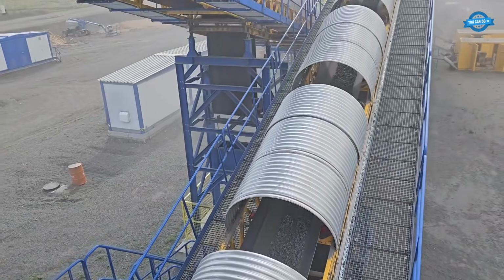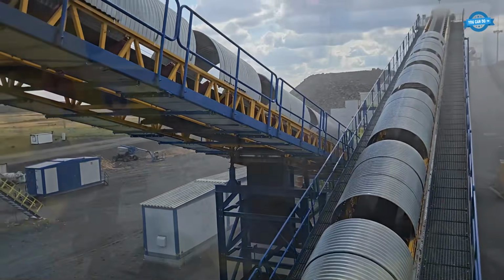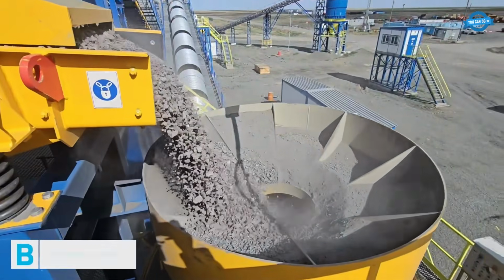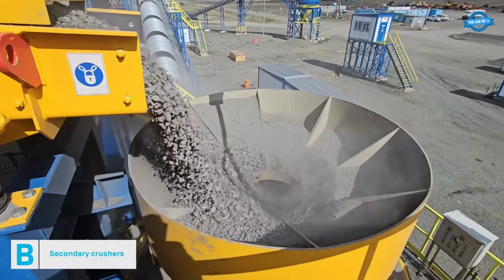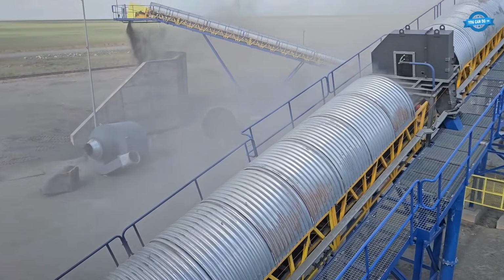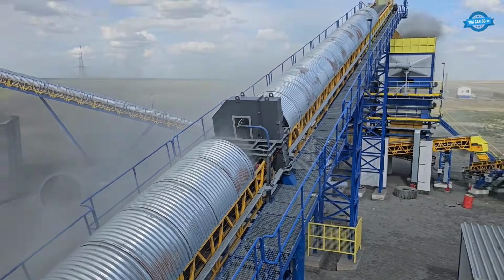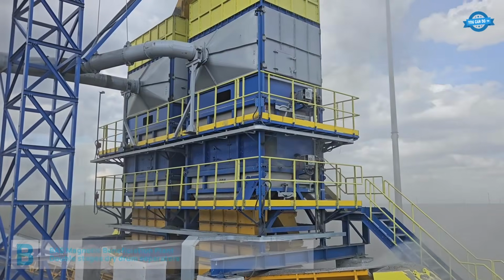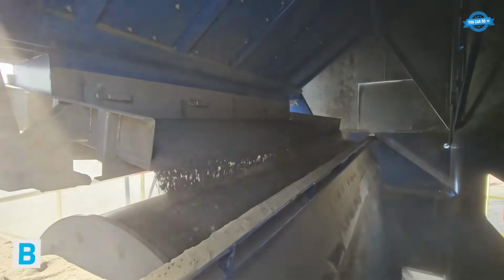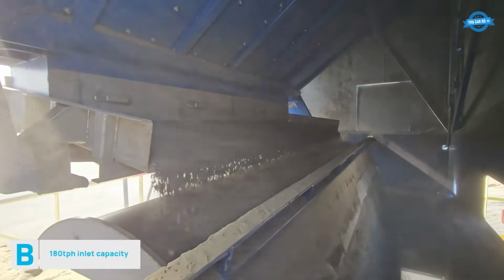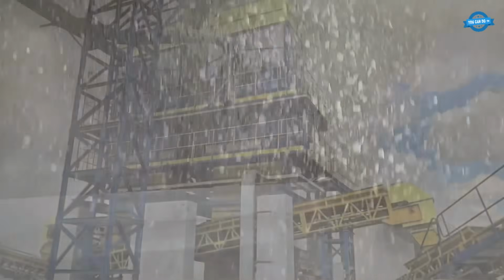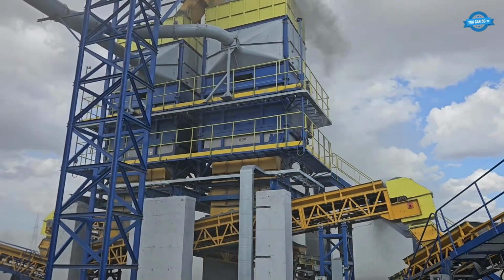Now put the whole idea into one plant at real scale, out in Central Asia. The raw feed lands at 360 tons per hour, sized up to 600 millimeters, running around 34% iron. Multi-stage crushing knocks the rock down. Screens sort by size. A specialty ore against ore separator handles the final stage and lifts the product to 54% iron. A 20-point jump in iron content is the line between a mine that eats steak and one that shuts down.